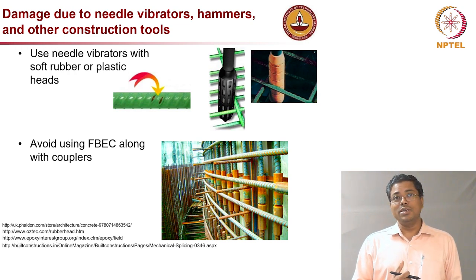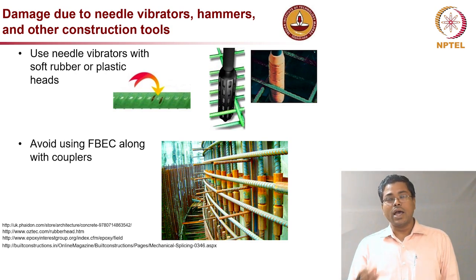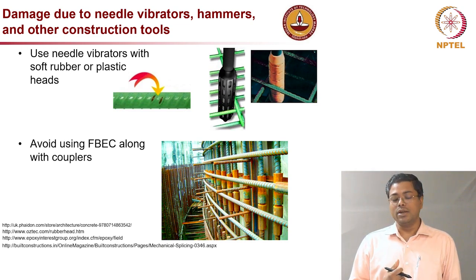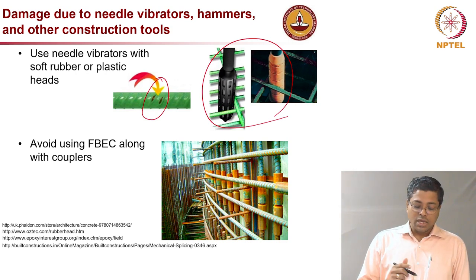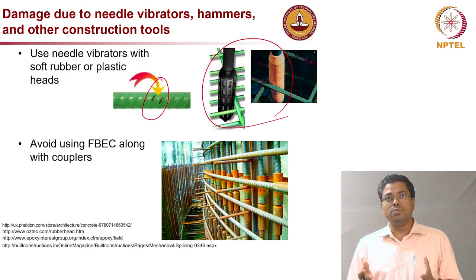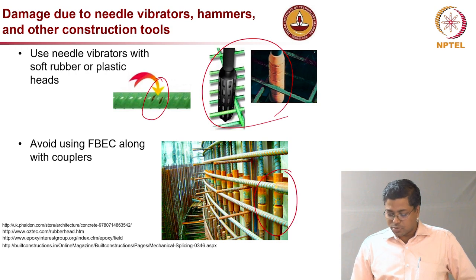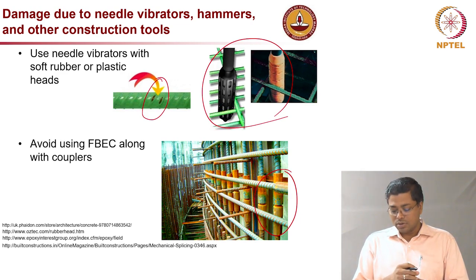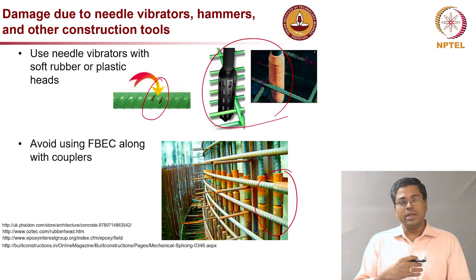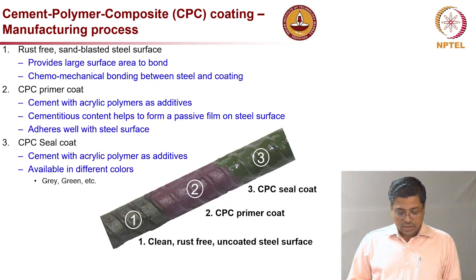For needle vibrators, metallic ones should not be used — the vibrator should have a rubber sleeve as shown in the picture, so that scratches are not induced on the rebars during the vibration process. This is a challenge because this process happens after the concrete is placed. Also, metallic couplers, when fastened onto the rebars, pinch and damage the epoxy coating.